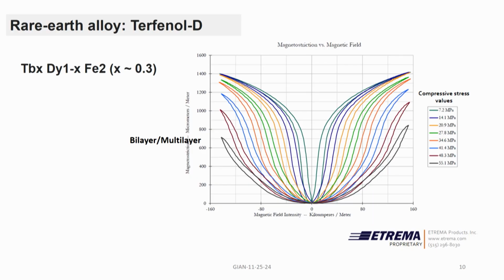This is Terfenol-D, the series of graphs. It is under different compressive strain applied to the alloy, just ignore it, but just look at the magnitude of the magnetostriction. It is quite high, on the order of a few hundred or 1,000, depending on the magnitude of the magnetic field, and it has terbium and dysprosium and a little bit of iron. But the problem with Terfenol-D is it is not easy to machine, and it is highly susceptible to oxidation. So, you have to protect the material with some kind of a coating, otherwise it will go bad. It will get oxidized in air and it is gone. Okay.